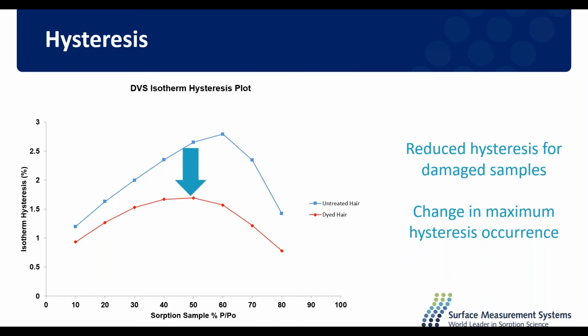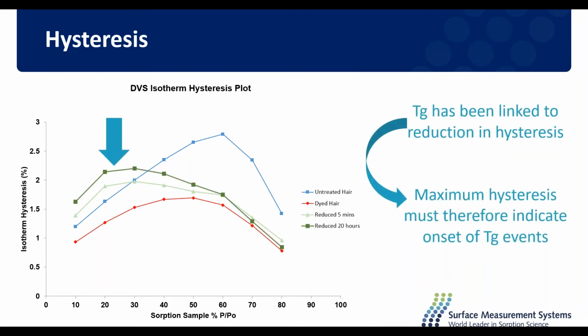If we now look at some of the reduced hair samples, we can see that that has shifted even further to 20% relative humidity for the reduced hair that had been reduced for 5 minutes. And then for the 20-hour reduced hair, we can see that that remains quite shifted over. So how does this link to swelling and to our glass transition?